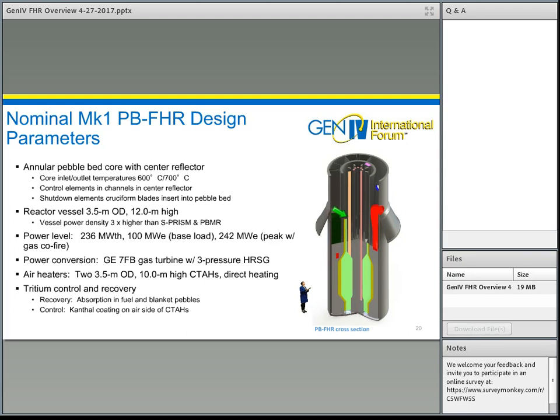The pebbles will be inspected and then in general recirculated a total of about 8 times before they reach full depletion and then are sent to spent fuel. Inlet and outlet temperatures are 600 degrees and 700 degrees in this design. The control elements are inserted in a center graphite reflector, similar to what was designed for the PBMR.